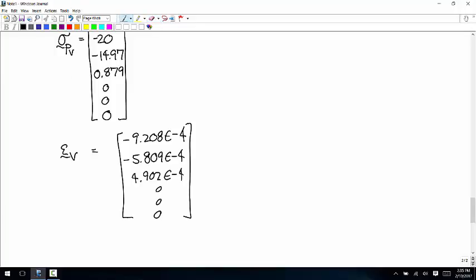Since the shear strains only depend on the shear stresses, and you know that the principal stress doesn't have any shear stresses, the strain in the principal coordinate system also has to have no shears. Which means that if you look at a cube that's originally aligned with the principal coordinate system, its deformed state is going to be changes in length, but no angle changes. So in the principal coordinate system, none of the angles between the sides change.